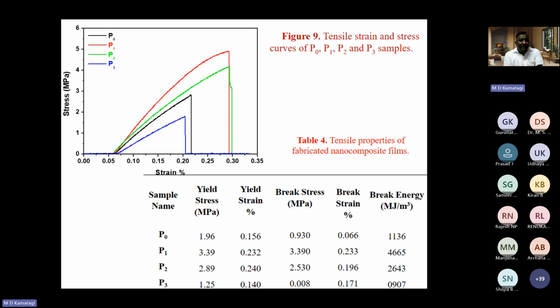exhibits higher stress. That means it can hold the higher strain. This shows that the doping of ZrO2 in polymethyl methacrylate greatly enhances the mechanical properties as well as the photoluminescence properties. Now, our work has shown that if you dope the PMMA with ZrO2, then its mechanical strength increases. That is a very good idea for denture applications.